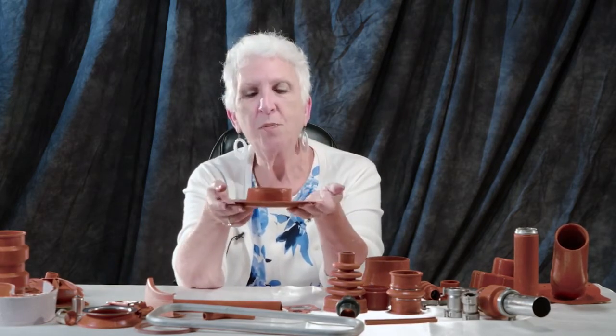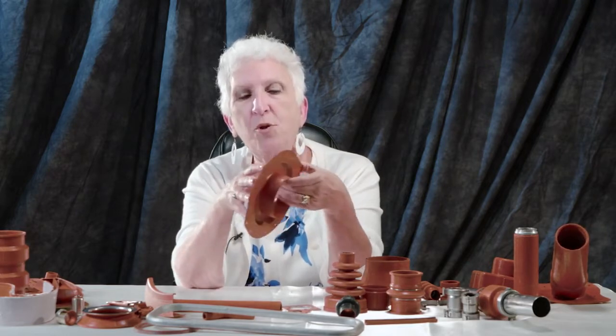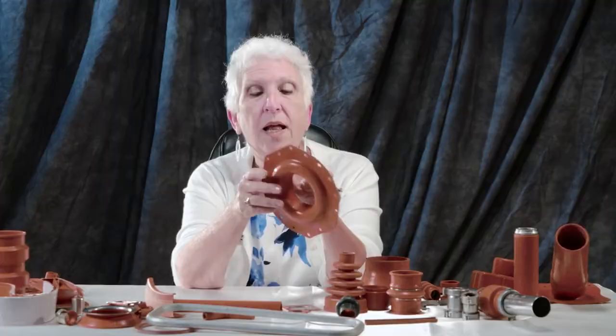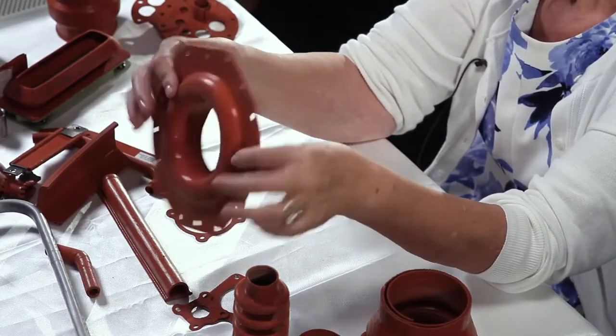This particular part has a whole book on it. It was a Gulfstream part. The FAA was about to ground the Gulfstream 4 and came to us to see if we could resolve the issue. It's an exhaust seal that couldn't stand up to the fire test. The reason is there's a flame on the backside, but the front side is under pressure throughout the burn for 15 minutes. Makes it a very stringent test. We passed the first time through and have never had a problem.